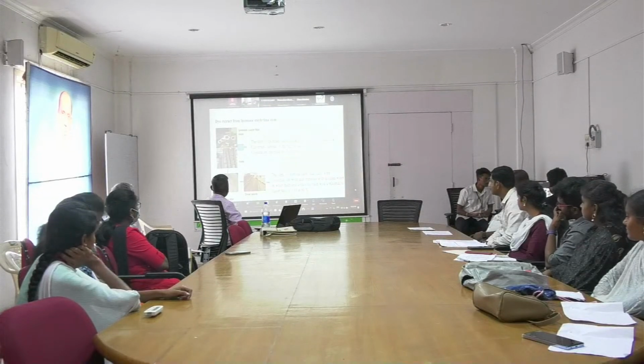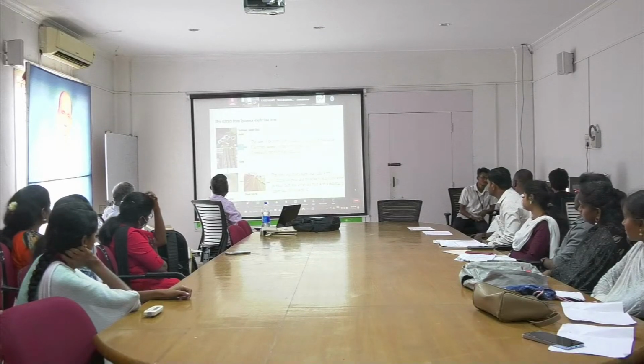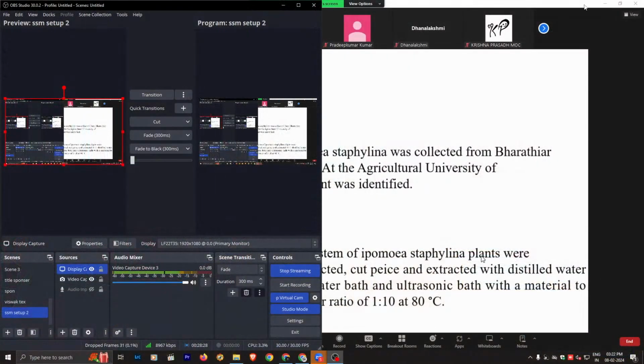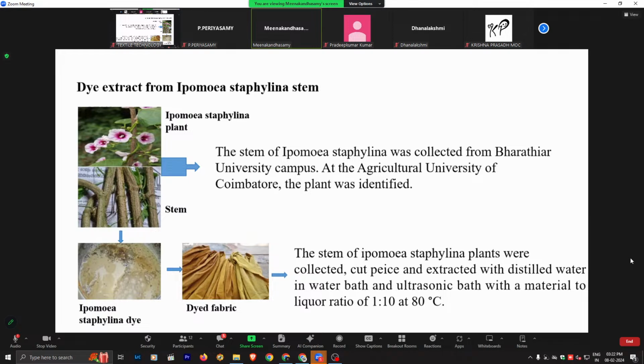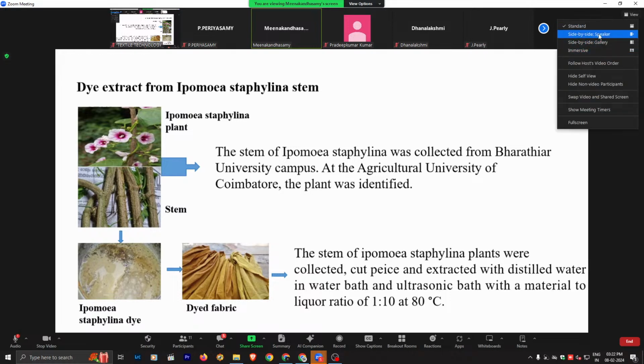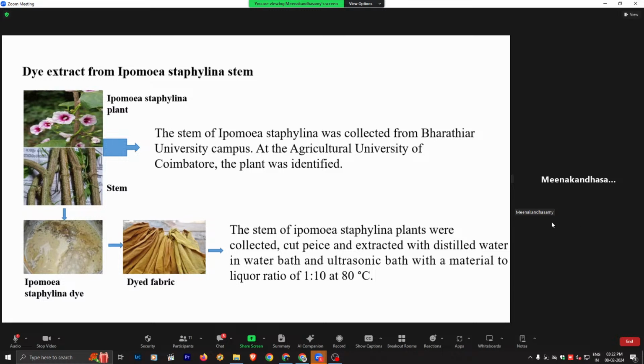The Ipomoea staphylina plant was collected from the Bharathiar University campus and identified at the Agricultural University, Coimbatore. The stem of the plant was collected, cut into pieces and extracted with distilled water in a water bath and ultrasonic bath, with a material to liquid ratio of 1:10 at 80 degrees Celsius. I have selected three types of solvent: aqueous, ethanol and acetone.